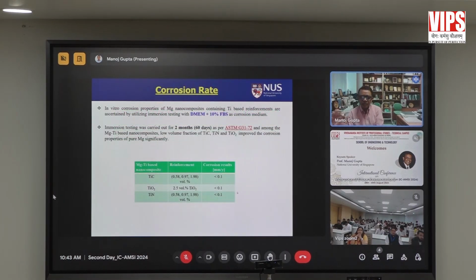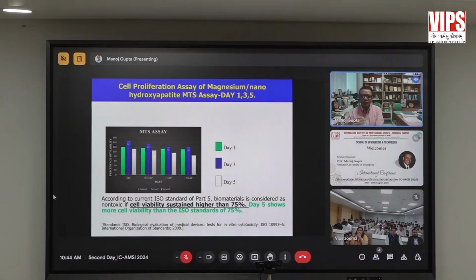And that is not enough, because when you put a material in the body, it has to meet two requirements: mechanical requirements and biological requirements. So we have to see how fast it's going to corrode. So we tested these materials in a biological fluid, DMEM plus 10% FBS, and we also discussed with doctors. So you need doctors in your team. And they said that any corrosion rate which is less than 0.1 millimeter per year will be suitable as a temporary implant. So we tried to do that.